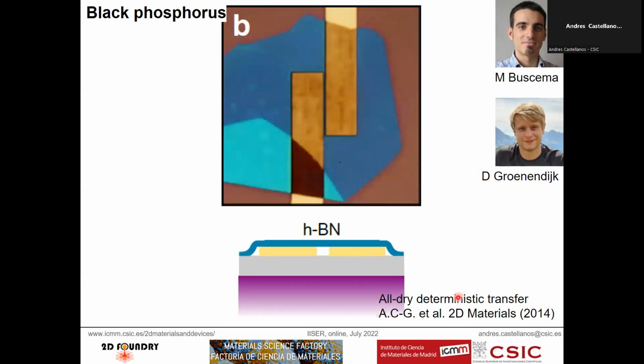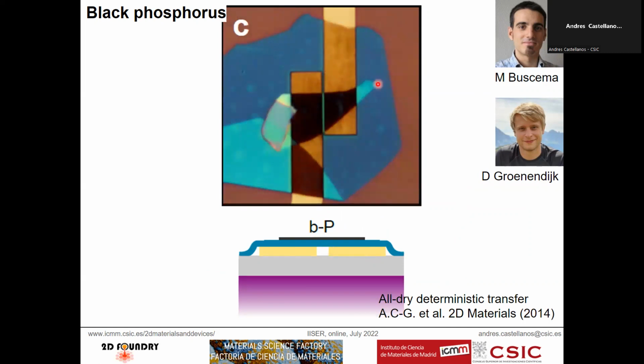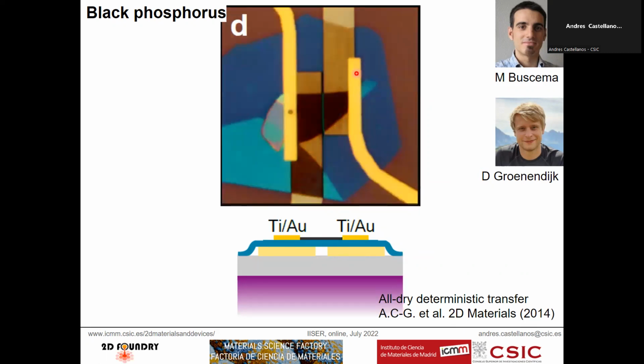Now, by using deterministic transfer, we can transfer a hexagonal boron nitride flake here. This hexagonal boron nitride is an insulating material. We transfer this boron nitride on top of the electrodes. Then we transfer a black phosphorus flake on top of the electrodes, but it is disconnected by the hexagonal boron nitride, so this works as a dielectric. And now we can go to the fabrication room again and put a pair of electrodes here.